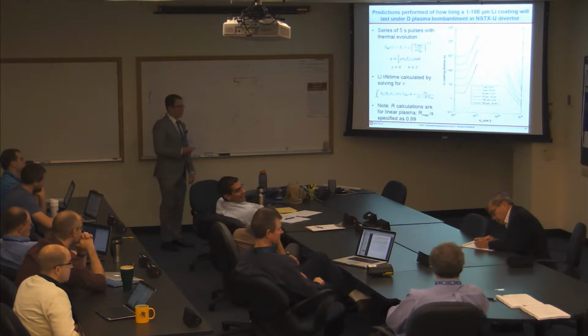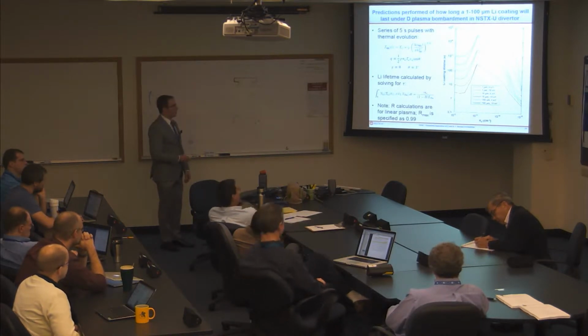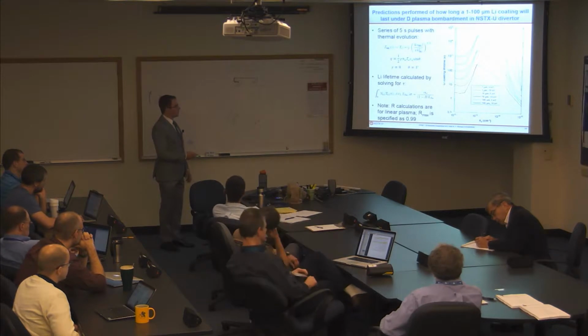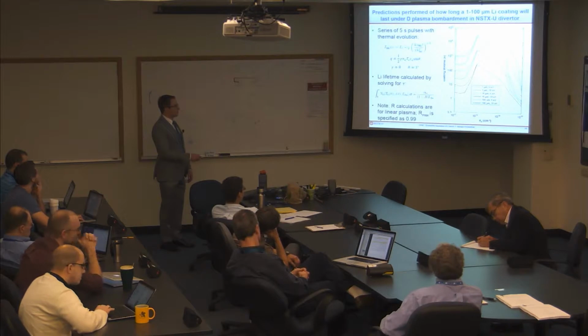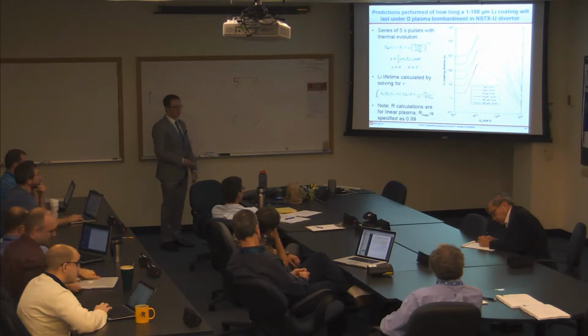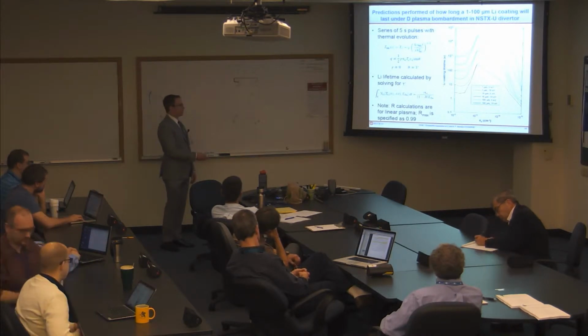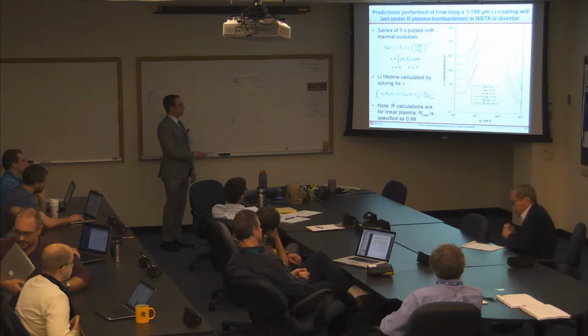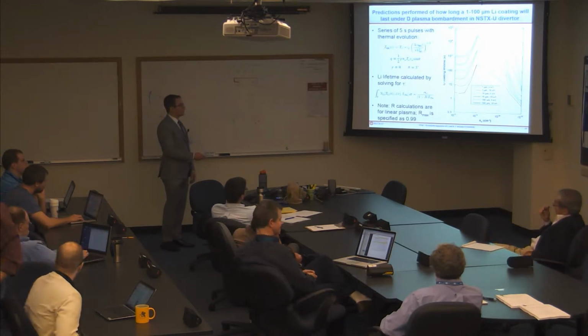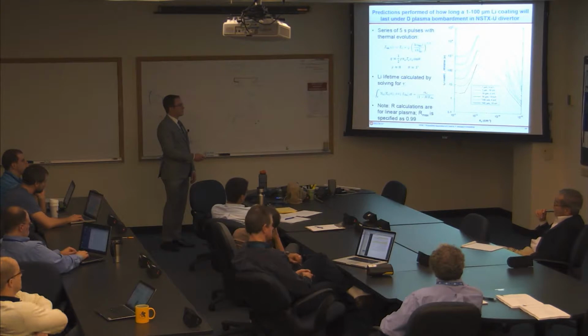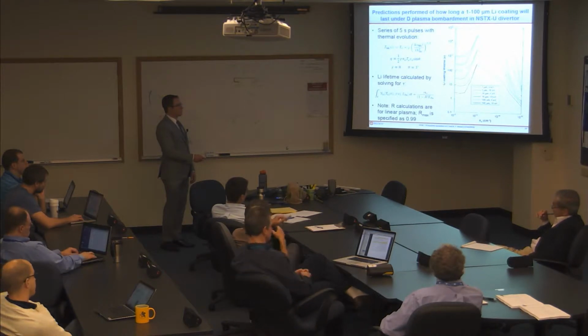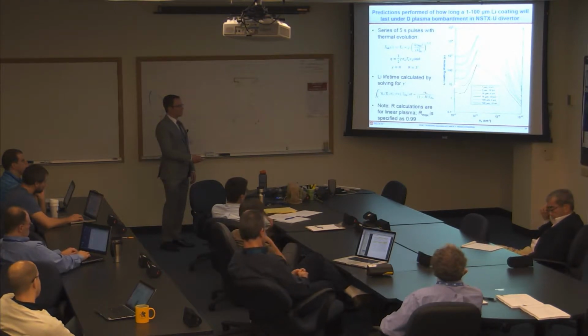So there's a lot going on here, and I didn't want to go into all of it. But basically, first of all, if you went to even lower densities, this is obviously going to go up again, because then you're at even lower fluxes, and so it takes an even longer time to deplete. But those are pretty irrelevant. So here it's more or less constant, and then this increase is because the redeposition fraction is increasing very strongly between about 10 to the 12 and 10 to the 13.